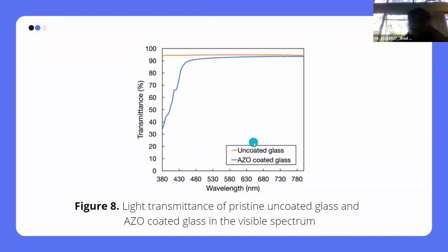This result, here we can see that the coated glass displays a lower transmittance curve at smaller wavelengths, because the amount of light that passed through the sample is less than that of the uncoated glass.